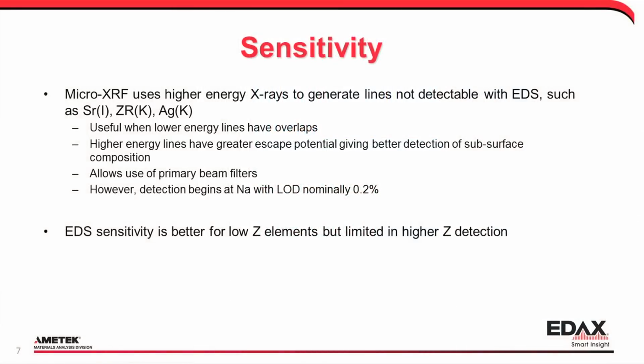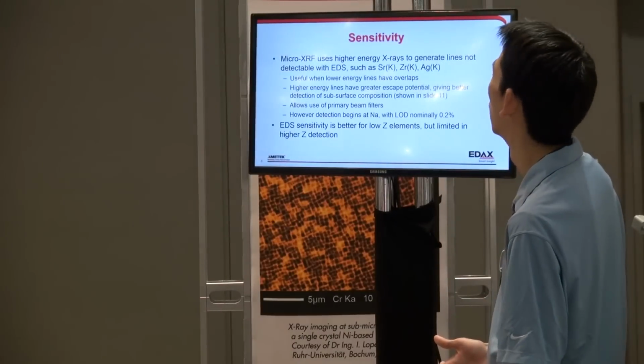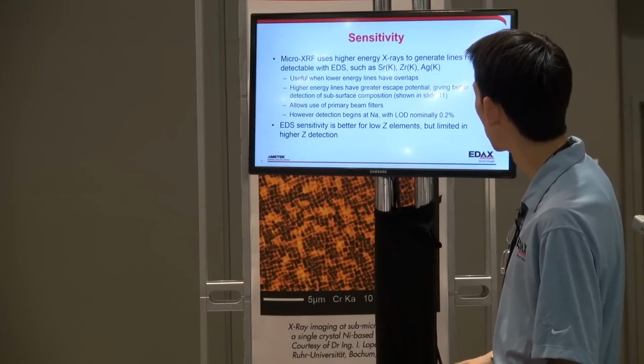Adding to the sensitivity issue is the fact that with micro-XRF, as we increase atomic number, we start to just use the K lines as opposed to reverting to the lower L lines. So in the instance of, for example, strontium, zirconium, silver, normally with EDS you would probably use those L lines to detect if it's present. And with micro-XRF, typically we have a tube that goes up to about 50 kV. The Orbis, that's the tube that we have on the Orbis, is capable of analyzing K lines for those elements, and that eliminates a lot of potential confusion. If there's an overlap with the L lines, you have the option of looking at the K lines to confirm whether it's present or not. So we'll take a look at that in the example in a later slide.